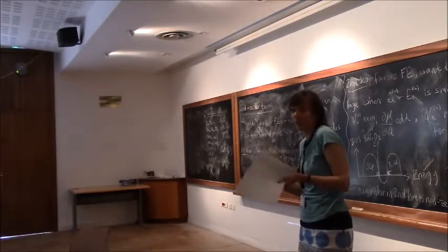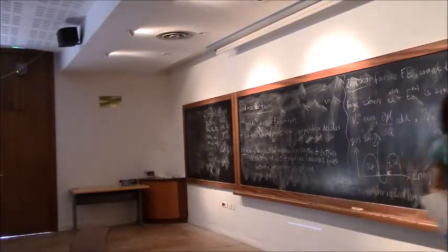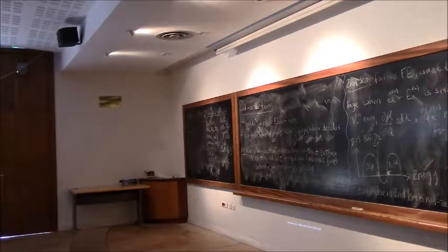Questions? Yeah. So it seems like a large gap will suppress ferroelectricity. Would a semiconductor maybe help ferroelectricity? By this picture, if you have the right symmetry and everything, if the gap is smaller, then this term will be larger. Of course, if you have a small gap, then you have lots of other problems like leakage. For example, germanium telluride has a very small gap and has a very large ferroelectric polarization. But that's a good point. Again, it's a competition, a balance. If the coercive field ends up exciting or making it metallic, then it's no good. So designing your ferroelectric by looking for the smallest gap would not be the smartest way to do it.